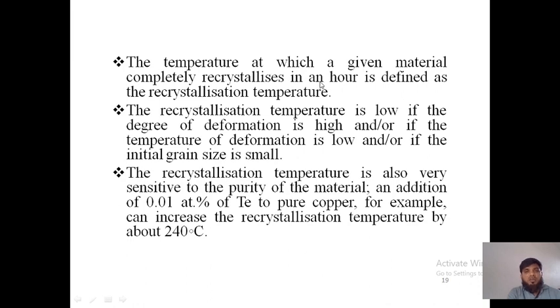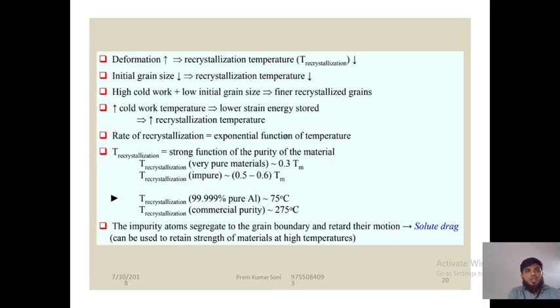The temperature at which a given material completely recrystallizes in one hour is defined as the recrystallization temperature. Recrystallization temperature is low if the degree of deformation is high — because large deformation creates more defects and free space, so atoms rearrange more easily. If deformation is small, fewer voids are created and higher temperature is needed. So as deformation increases, recrystallization temperature decreases.